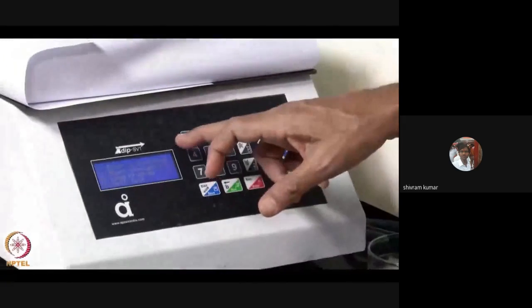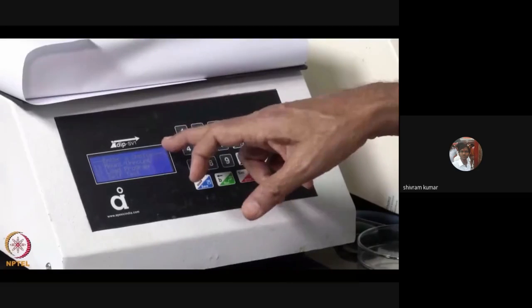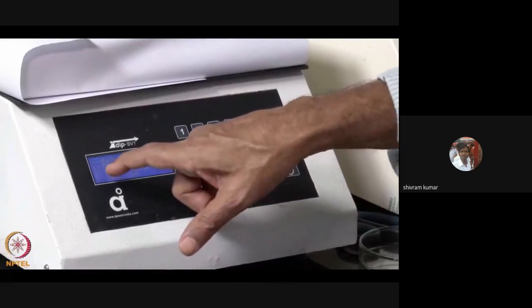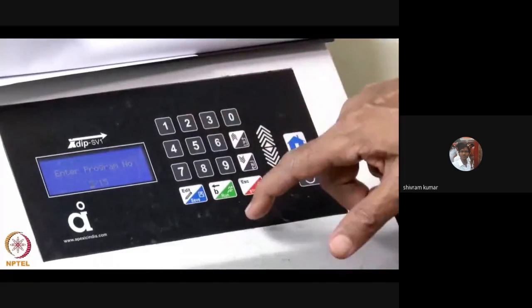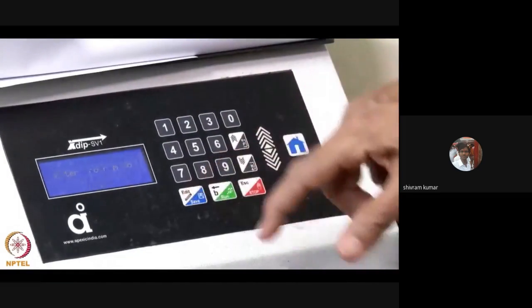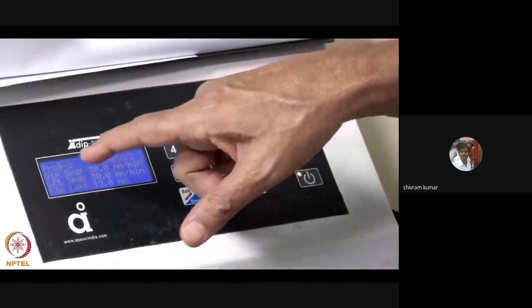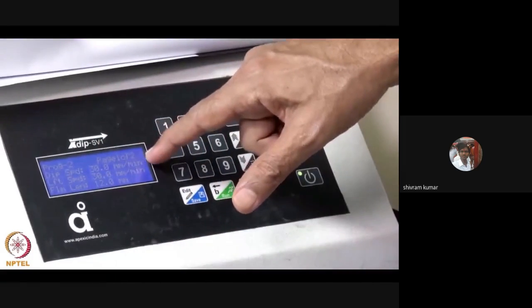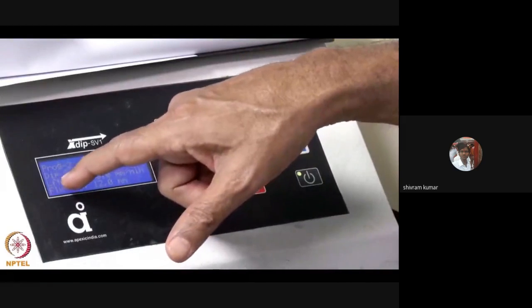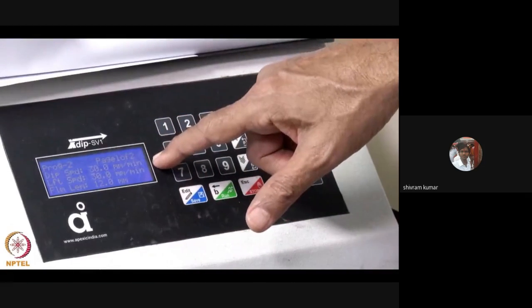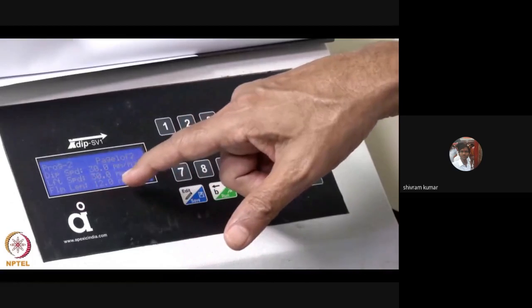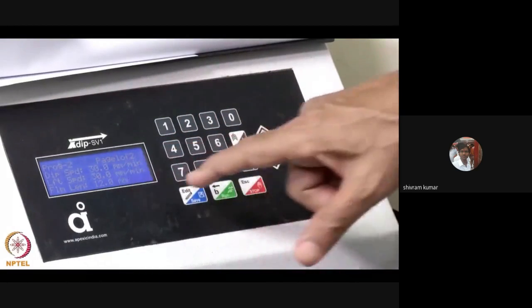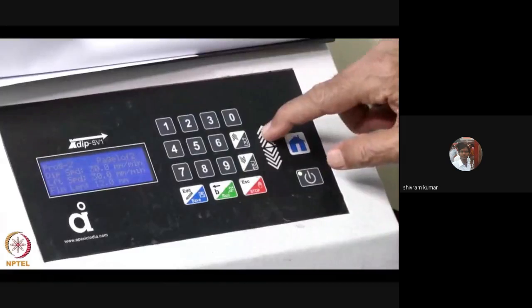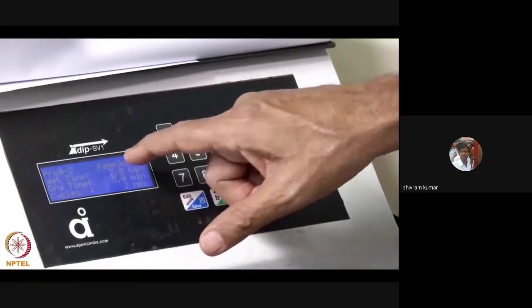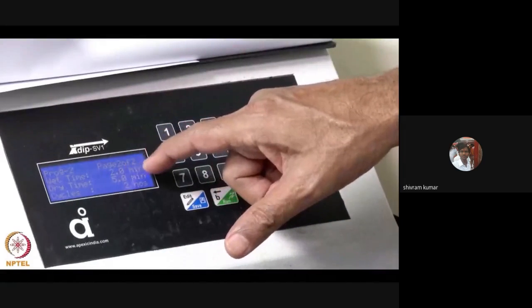Here is where we set the program for the dip coating. I already have a program, it's called program 2. It gives the dip speed, millimeter per minute. It gives the lifting speed, millimeter per minute. It is giving the length of the film, that is how long the film is. It gives how long the dipping has to be in minutes.